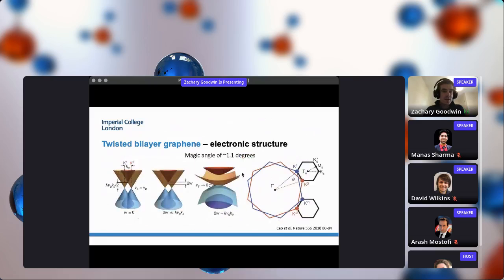And so what happens to the electronic structure of these graphene layers upon stacking and twisting them? Well, simply what happens is twisting one layer relative to the other one shifts the Dirac cone of one of the layers in momentum space relative to the other. So what we have, if these graphene layers don't talk to each other, is just 2 Dirac cones shifted in momentum space. But because these graphene layers are stacked on top of each other, they can hybridize with each other, and this causes the spectrum to change slightly.